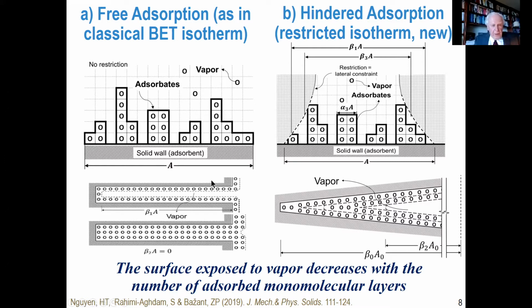Now there is a difference, however, which explains why BET isotherm works only for small humidities, but grossly mispredicts for high humidities, close to saturation. It has to do with the nature of filling of nanopores. So what matters for calculations of the adsorption is the surface exposed to vapor. The blank is vapor, and we show layers of 2 molecules thick, water molecule thick, which is about half a nanometer. And obviously, as the pore of a wedge type is getting filled, the area exposed to vapor is decreasing.